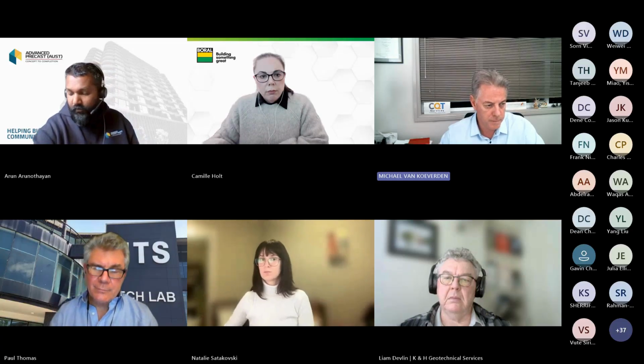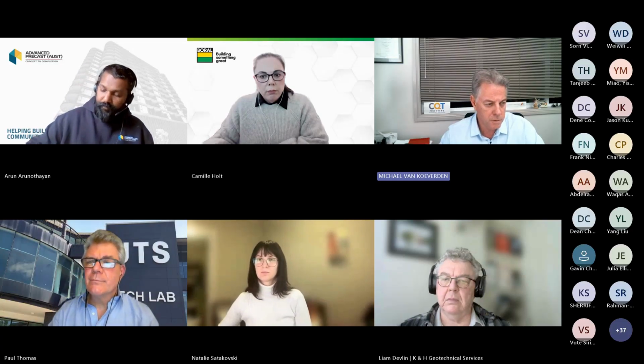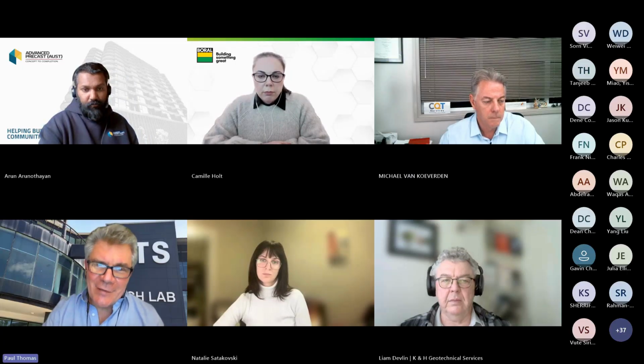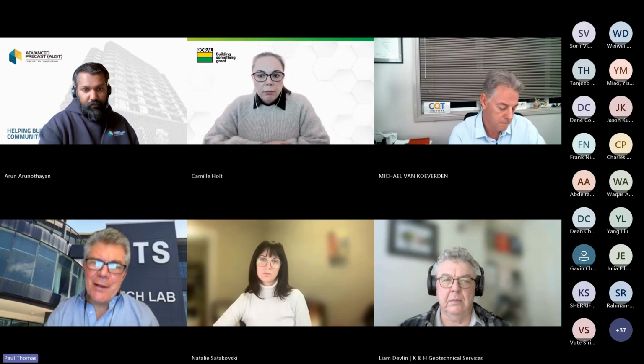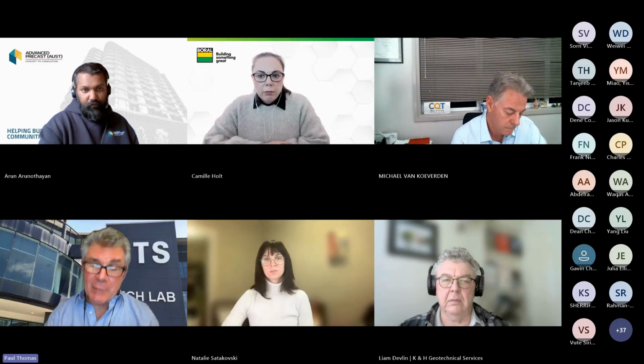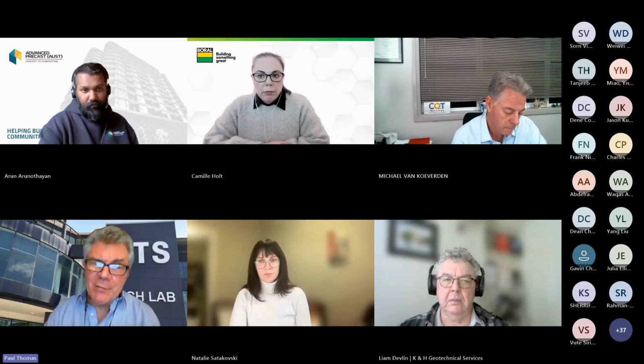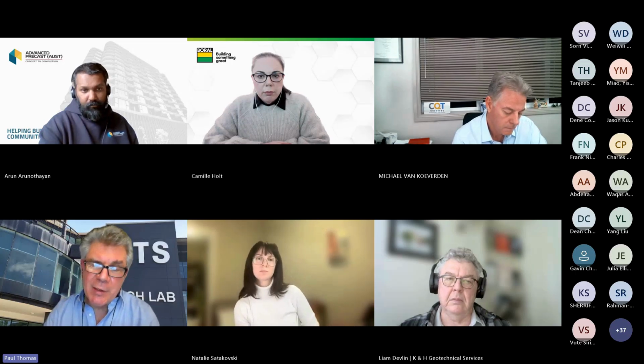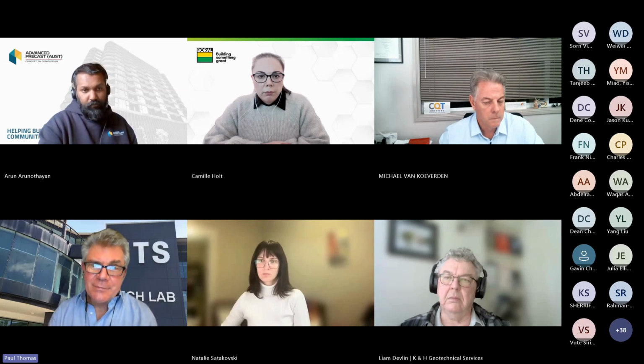Thanks Paul, my only follow-on is the surface area of the material - do you have a big difference in surface area between the two in terms of area for reaction? Yes, because the calcined clay is higher - the particles can be smaller, but fly ash is a glassy spherical substance, not quite geometrical, but it has a fairly low, relatively speaking, lower surface area.